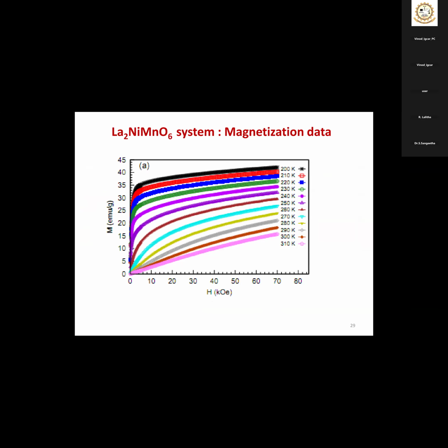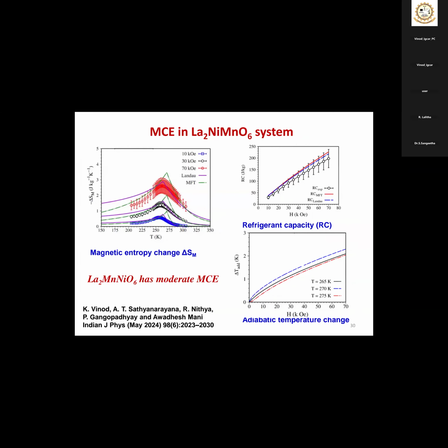Routine measurement, magnetization versus field. Simple isothermal magnetization data, this we can convert into magnetocaloric data. Here we have shown isothermal entropy change, refrigerant capacity, and adiabatic temperature change. For adiabatic temperature change, you need heat capacity. For the present work, we have done some calculation. That is why there is a symbol plus the line also. The line is based on calculation. That calculation part I skipped.